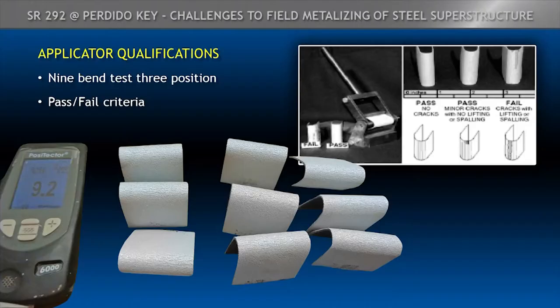These were actually the bend tests that the applicators had to qualify to. 9 bend tests, they had to have three at three different positions: vertical, horizontal, and overhead. And they were asked to put them on at about 8 to 10 mils. And then they were bent across this mandrel, half-inch mandrel, and they were checked for cracking. And you see the last one up there, it's not very clear, but you can see the cracking at the top of it where the metalizing is split.